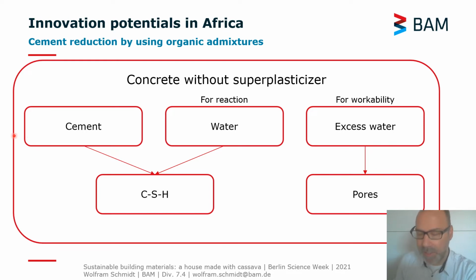Now, the other part I was talking about, when we use chemical admixtures, we have to see that in a traditional concrete where there's no superplasticizer used, cement and water are added for the reaction to form, for example, calcium silicate hydrates. But unfortunately, the water amount that is required for the reaction is too low to provide a good workability of the concrete. So even though we could theoretically achieve a high strength, when we cannot compact it, we cannot really use it. So we have to add excess water that provides workability, but when this excess water, which does not react, evaporates, it forms pores, and that reduces the strength of concrete.